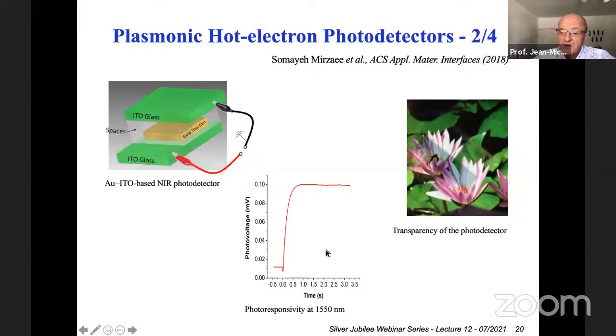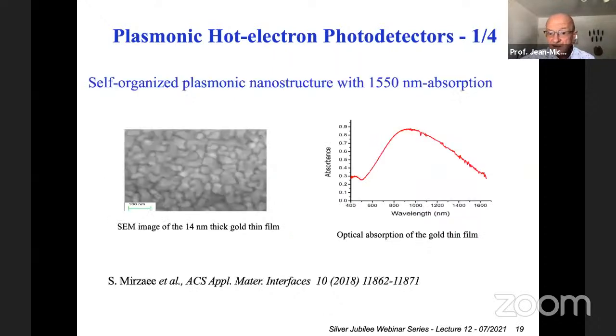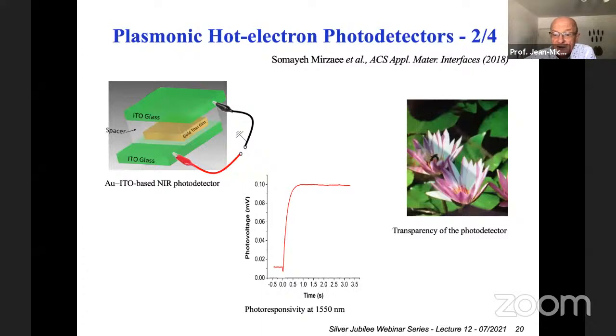So if you want to have a hint into how the photodetector is working, the light that is polarized in the plane of the film will couple to this localized surface plasmon resonance between these nano aggregates that you see on the SEM microscopy figure here, and they will create these charges and will eject hot electrons. I will come back to the ejection of hot electrons, which will then change the polarization inside the capacitor and create the photovoltage that we have in our detector.